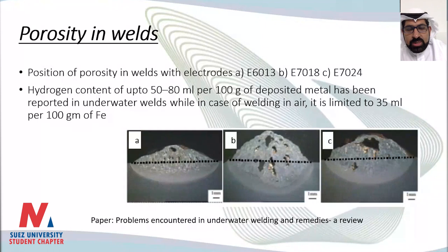Next, please. So porosity also, the porosity position, as we said, you're using E6013, which has little hydrogen. E7018 has hydrogen in it. E7024, this is an electrode that you use in shielded metal arc welding. So these electrodes have some hydrogen in them, plus the hydrogen they will create and get from the wet environment. So hydrogen content in the water is measured between 50 to 80 milliliters per every 100 grams of material. However, if you compare it with the hydrogen content on the surface, it is about 35 milliliters, which is way less than the one underwater, which is obvious.